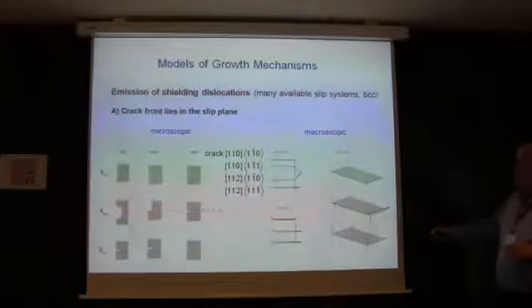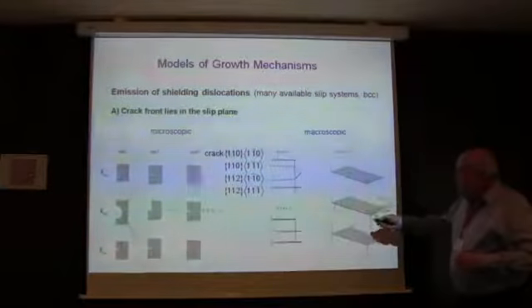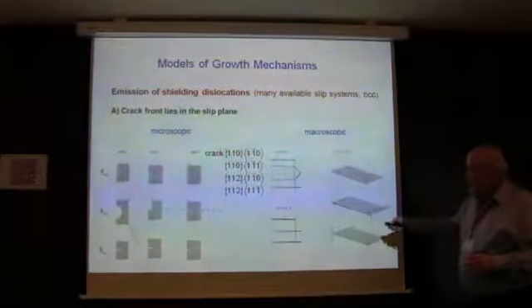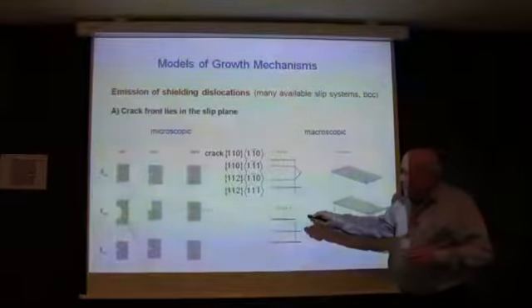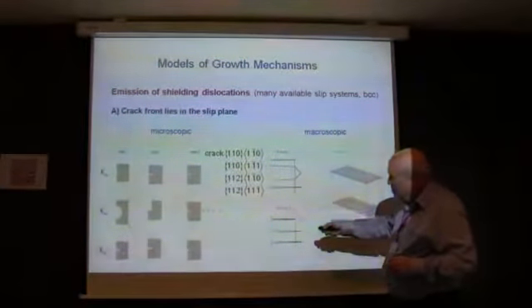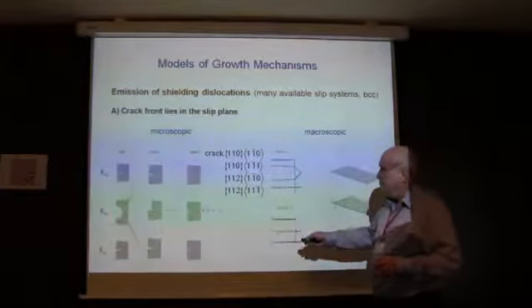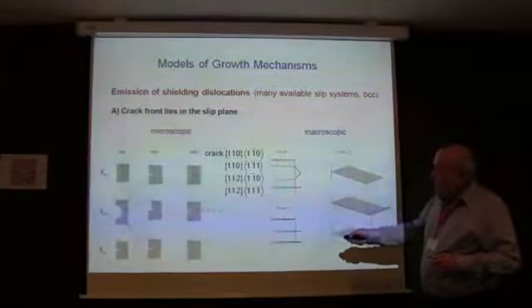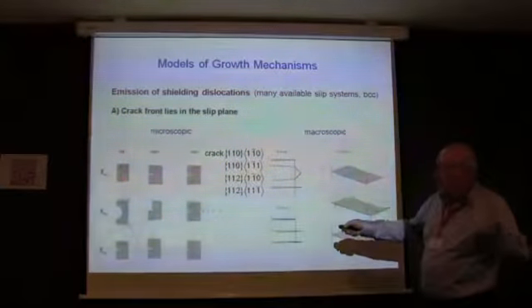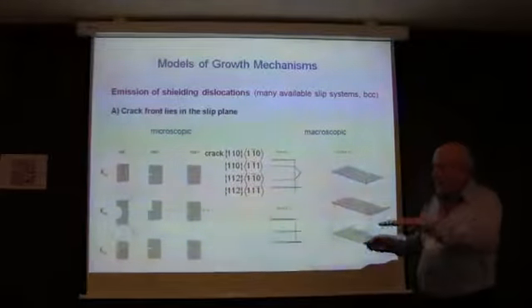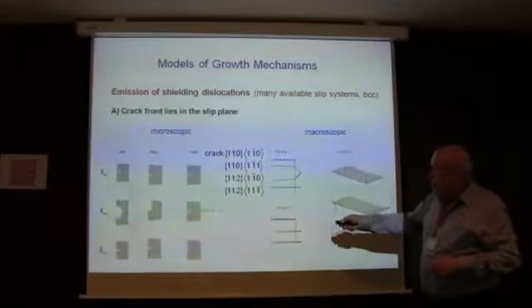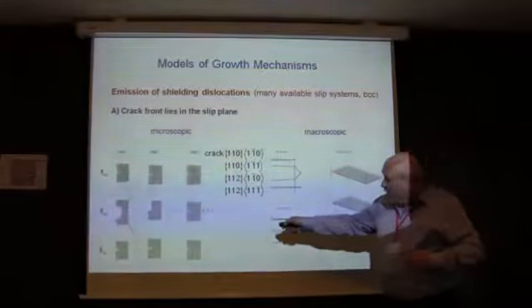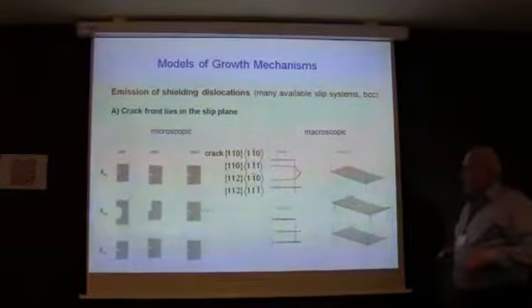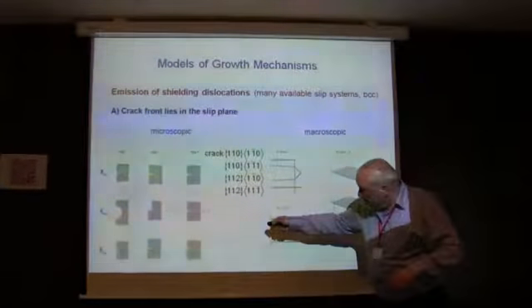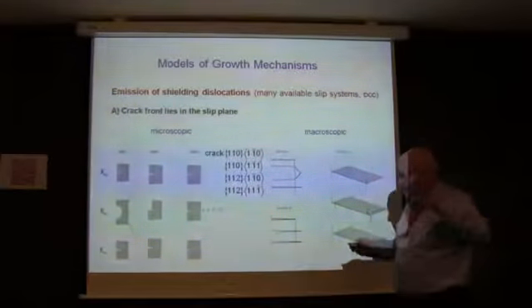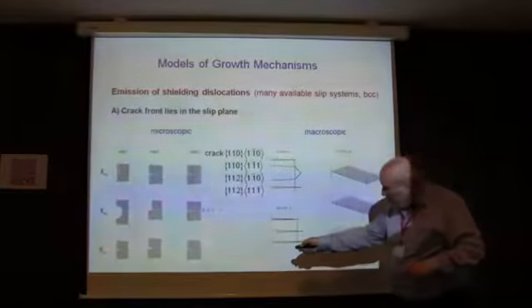This is the simplest, well-known case. You can have a crack slip configuration like this for BCC metals. So in mode 1, this is blunting by emission of edge dislocations, shielding dislocations, and then new surfaces are created here. Mode 2, the same happens in shear: emission of in-plane edge dislocations, and again creation of some new surface which is not recovered, just by the environmental effects and so on. And you can get the crack propagation.